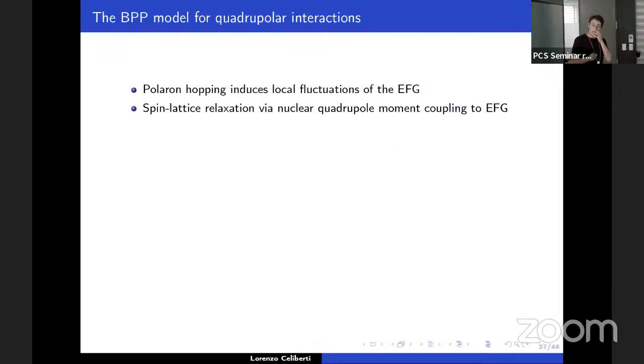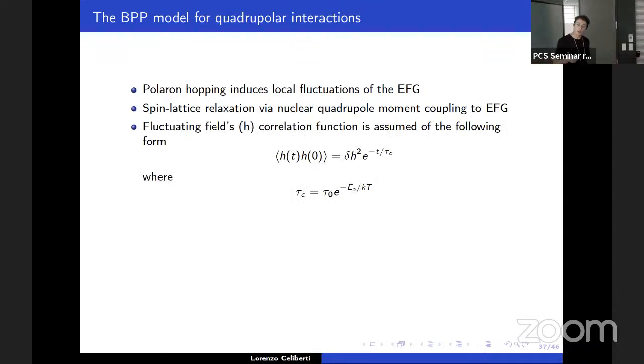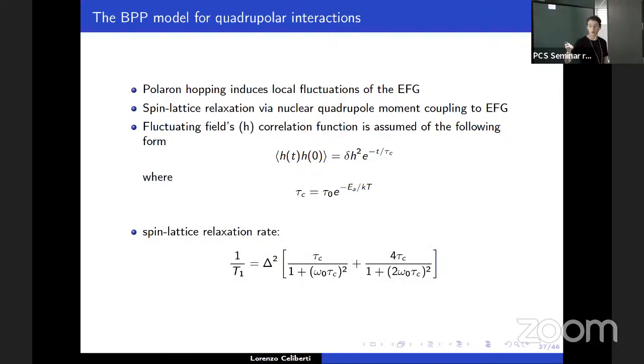Yeah, so basically we can model this relaxation, this quadrupolar relaxation, and you assume that your perturbation has a correlation function which decreases exponentially with time and is characterized by a correlation time tau. This is usually standard, like in NMR experiments where you have some kind of lattice motion driving the relaxation. What you get is this formula, which is called the BPP model, a standard from the 50s, where you have omega 0, the Larmor frequency, the correlation time, and the parameter delta squared, which is related to the height of the peak. So using this model, you can extrapolate the activation energy for the hopping process.